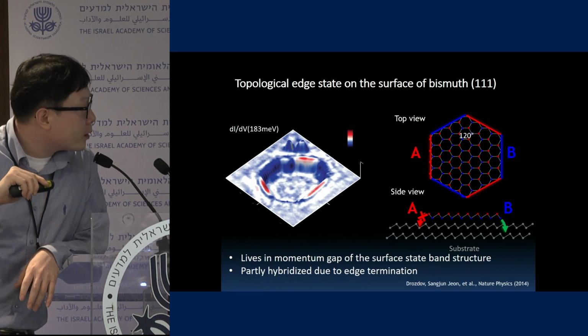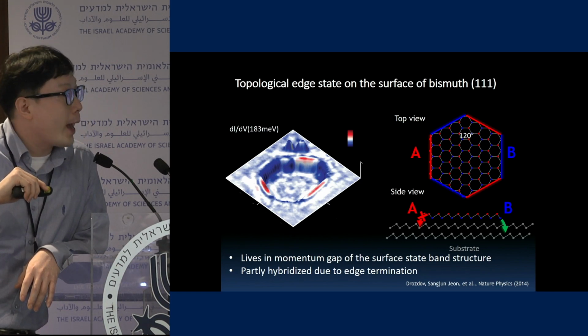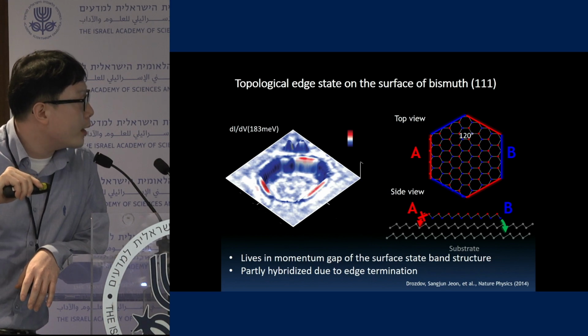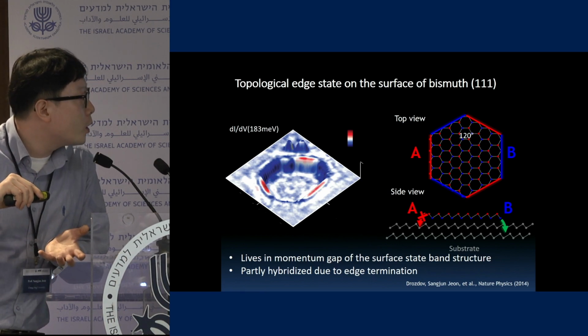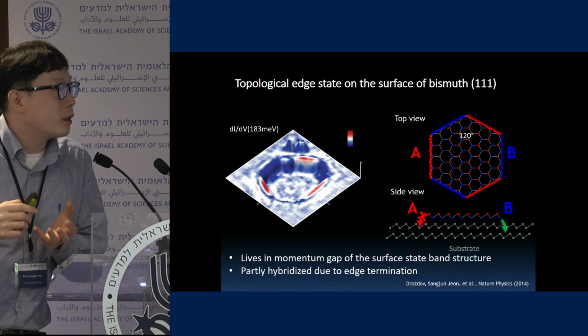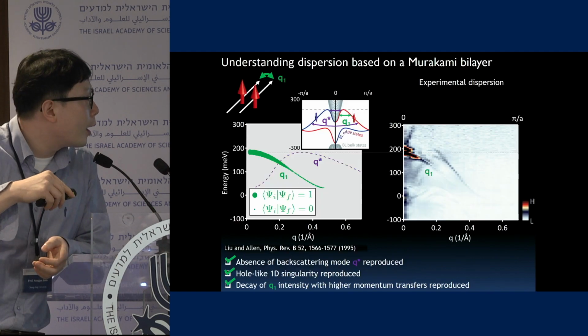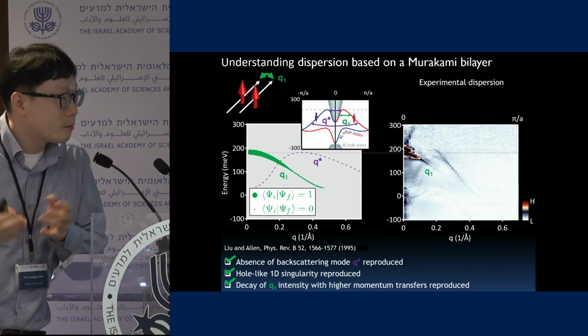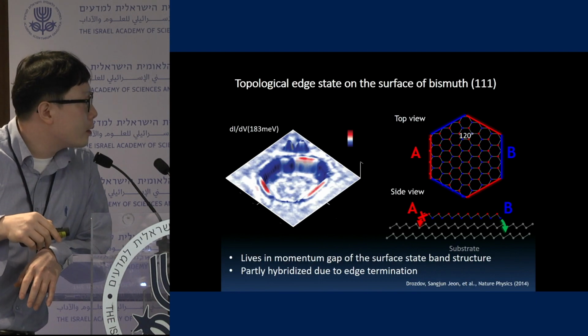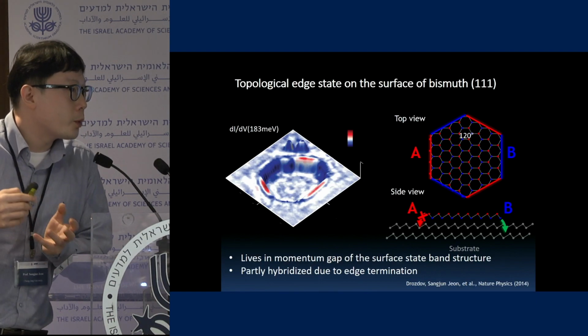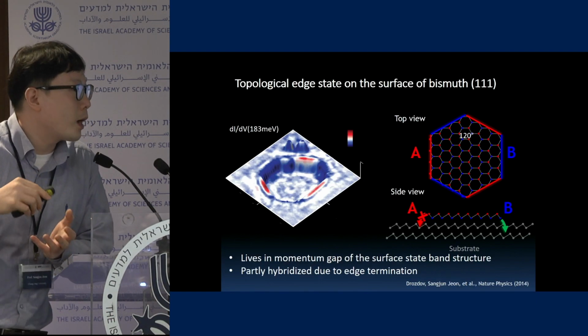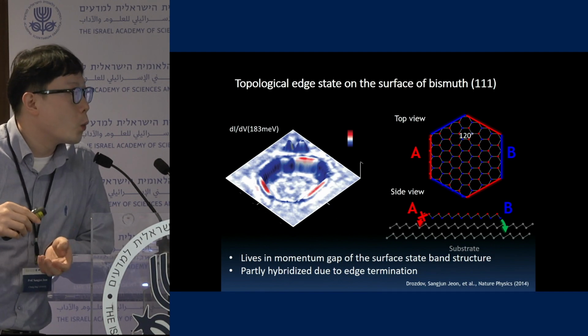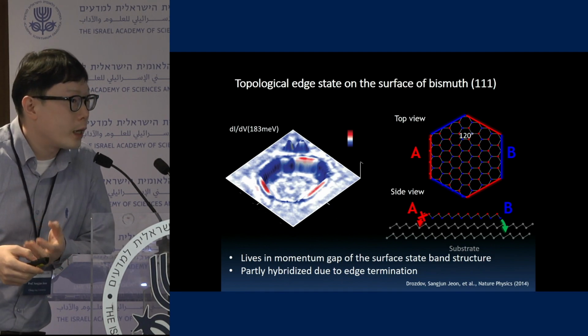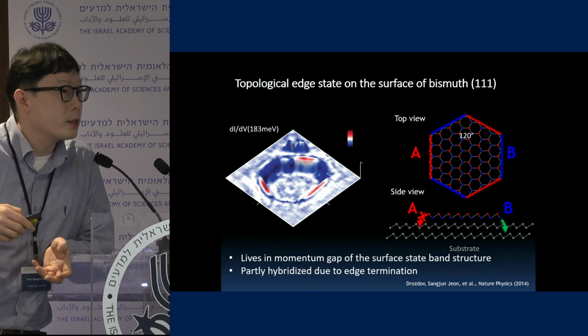One interesting part is that we found two different kinds of edges. We call them A edges and B edges, and somehow only one side of the edge gives us this kind of localized helical edge states. At the moment, we didn't know much about it, so we thought that this is some kind of hybridization issue. One side is strongly hybridized to the bulk system, and the other is not the case.